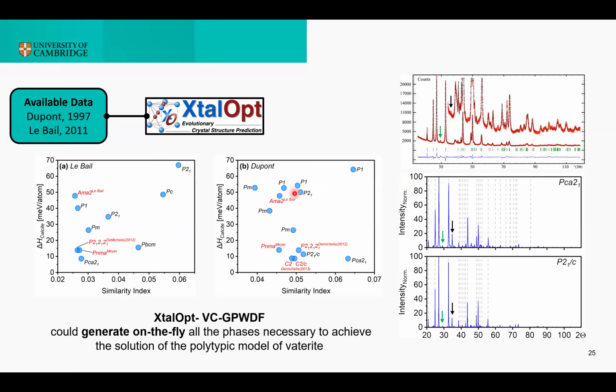The take-home message in this case is that even if pure structure prediction cannot directly solve this kind of difficult problem, with our method we could generate almost on the fly hundreds of thousands of structures and more, sorting them by energy and similarity index with the powder diffraction, which I believe could become an important complementary support for experimentalists when they undertake very challenging crystallographic problems.